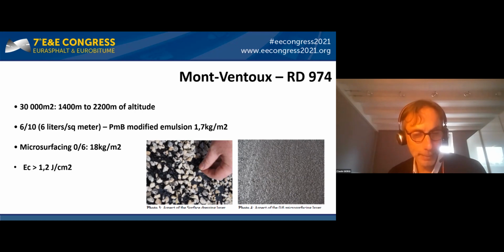This pavement was degraded mainly by surface cracking related to the aging of the pavement. Combined layers was proposed as an original solution with the double interest of being both economical and to perfectly meet the need of the department council, sealing the road while ensuring a sufficient level of adherence. The choice was made of a first application of a latex modified emulsion at 1.7 kilograms per square meter with a 6/10 millimeter sand lime gravel at 6 to 7 liters per square meter application rate. Then a microsurfacing layer was applied at 18 kilograms per square meter. The microsurfacing layer was applied about 2 hours after the first layer.